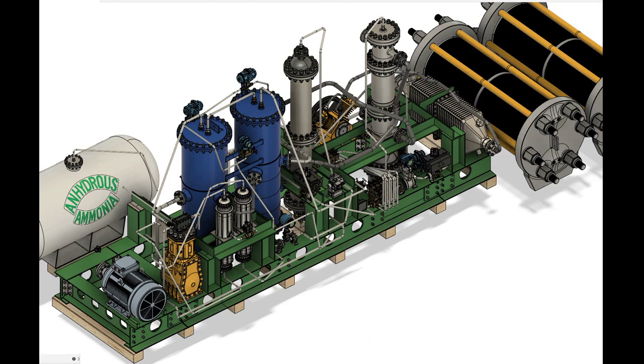Other than changes in thermal flux, a small penalty will be encountered due to the phenomenon of roughness-induced turbulent pressure drop. Since a small plant uses hosing or piping that are smaller in diameter, the roughness of these internal passageways will cause a pressure drop across the circuit, and since the ratio of surface to volume is greater, more gas will be exposed to the rough outer surface and will become turbulent, causing its velocity to increase and pressure to decrease. This can be mitigated by using extra smooth internals, or keeping the gas-hourly space velocity at a lower number.